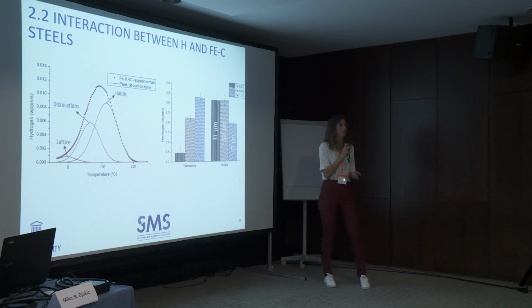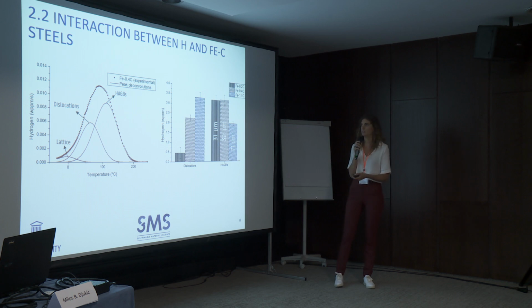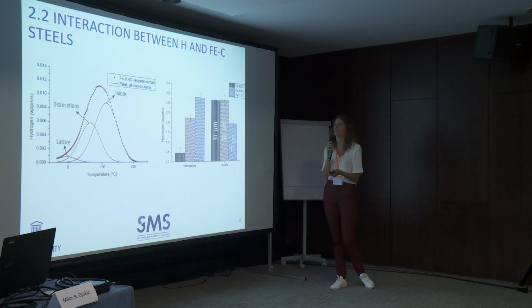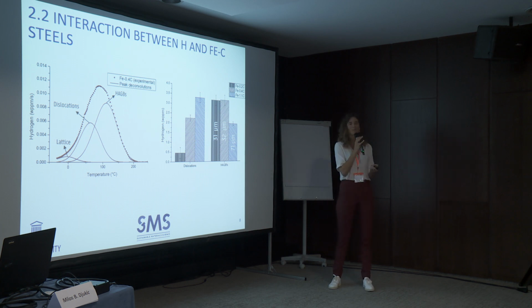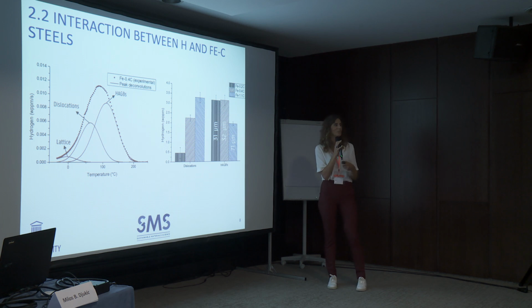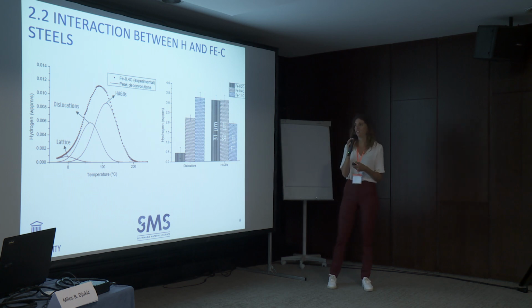So first, before I do the mechanical testing, I see where hydrogen is trapped inside these materials. This is an example of a TDS curve of an iron 0.4 carbon steel, and we see that there are 2 main trapping sites, namely the high-angle grain boundaries and the dislocations. This is investigated by comparing the activation energy with activation energies found in literature, and also by applying several heat treatments to see how these trapping sites change. And we can quite surely say that these are the high-angle grain boundaries and dislocations.